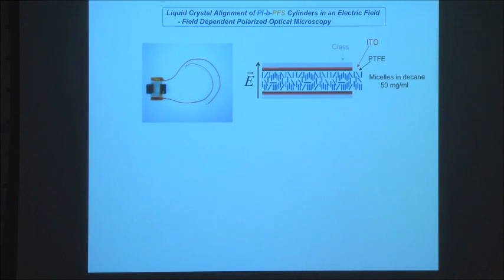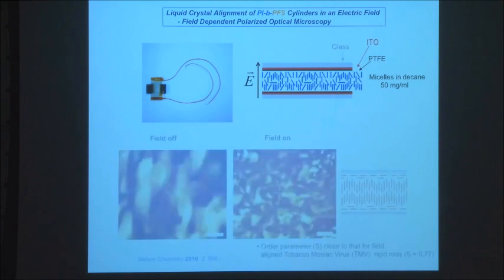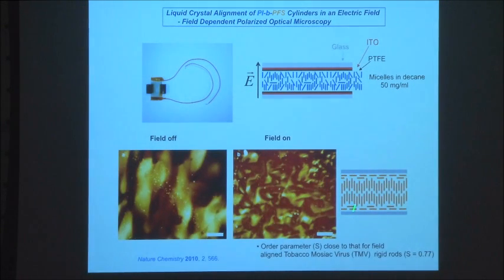And you find that if you take a concentrated solution, they will tend to align, so they form nematic liquid crystals. And if you use an electric field, you can make them align really very well. And you can get very good order parameters where they will align with an electric field going across here. This is all done in this little cell here. And you can get alignments here that are very similar to the values you can get with tobacco mosaic virus.